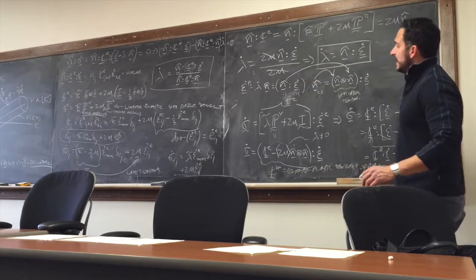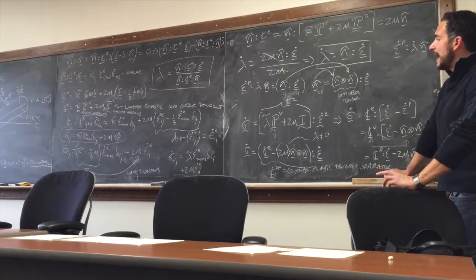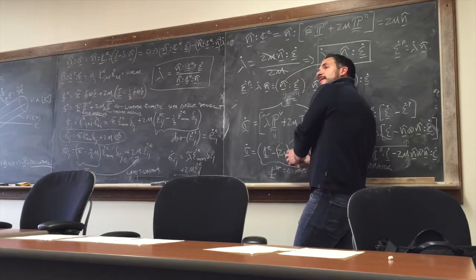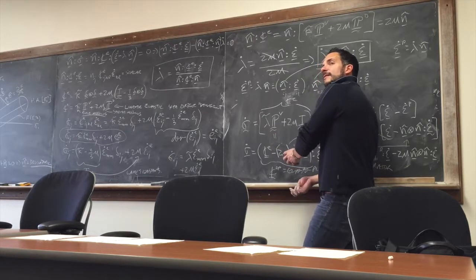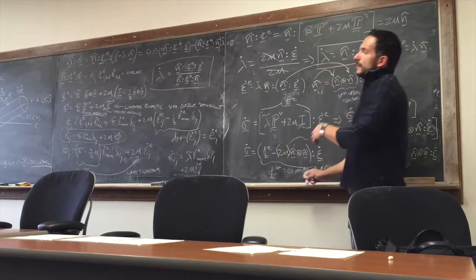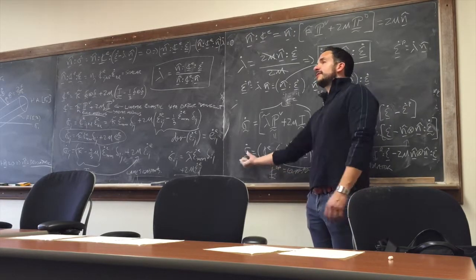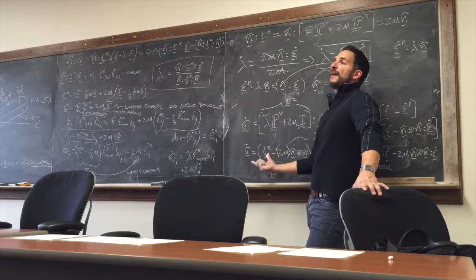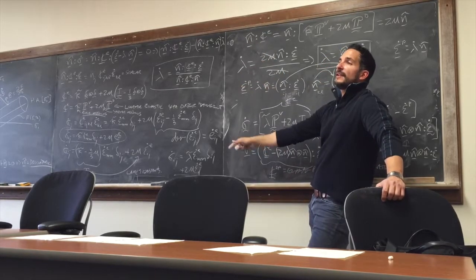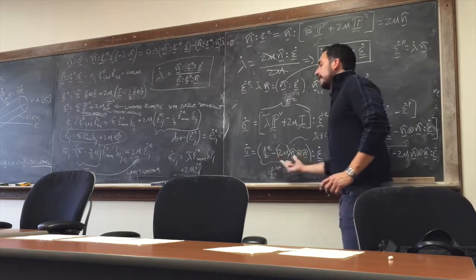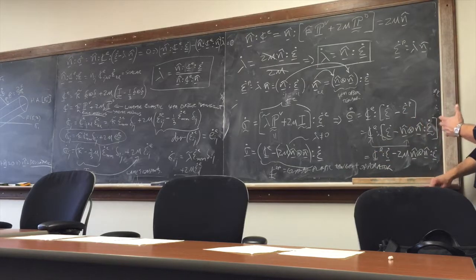Okay, I'm going to stop there and essentially say that you can start to see where the algorithms came from as well, because you can start to see that there's a portion that is elastic and then it gets corrected, right, or fixed given your plasticity constraints. All right, so the trial part of the algorithm can always start by assuming that this is 0, for instance, and taking the first approximation by making the first increment just elastic, and then finding out if that doesn't violate any of your ingredients, let's say consistency. And then if one of those is violated, then it comes back and it corrects. Okay, but you can start to see this very nice structure that is almost additive, where you have something that looks very elastic and then you fix it or correct it with something else.